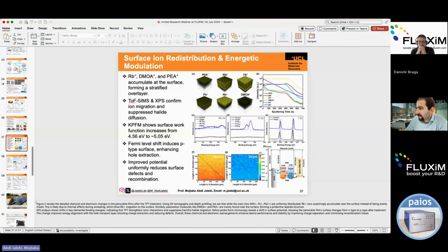Sure, that's a very good question. We have utilized this ToF-SIMS measurement that can give you an elemental map of your material cross-sectionally. Panel B shows the concentration of different elements, including rubidium, from the top surface deep into the bulk. It's a surprising discovery because we weren't expecting rubidium to appear at high concentration at the top surface, where we added it at the bottom surface.